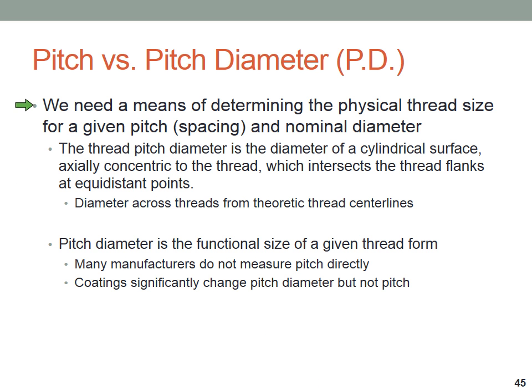So aside from pitch or spacing, we need what we would consider just a functional size. How do you measure the pitch diameter? Pitch diameter is essentially if you were to draw a cylinder through the plane of the threads, concentric with the threads, intersecting the thread flanks at equidistant points, that would be the pitch diameter. It's a complicated thing to measure and a complicated thing to understand. But essentially it's the diameter across the threads from theoretic thread center lines. This gets a little bit complicated because we're talking about theoretic thread center lines, not actual thread center lines. Pitch diameter is the functional size of a given thread form.